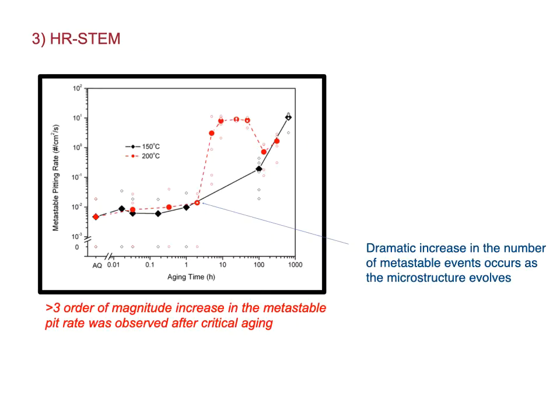In terms of advances in high-resolution scanning TEM, inclusive of aberration-corrected microscopes, such microscopy was utilized to assess the microstructural origins of what happens to a microstructure when the rate of pitting changes, and here in this image you see it being measured electrochemically using the potentiostatic method for electrochemical analysis of metastable pits.